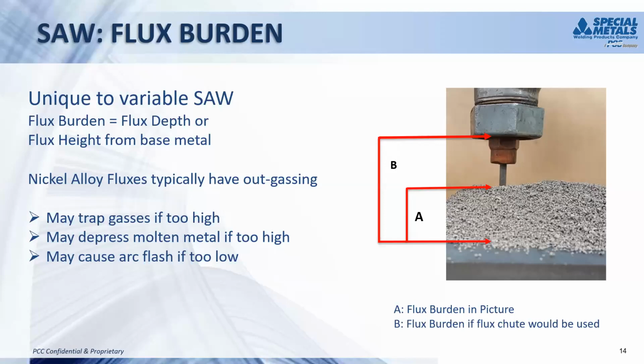If that burden is too low, you do tend to get a little bit of arc flash. Too much of that can be detrimental to the operators, but there are a couple scenarios with some particular nickel alloys that solidify very quickly, where most of the guys that run that in submerged arc do actually want to see just the hint of a little bit of arc flash coming through, because they want to just barely cover that weld puddle so they don't trap any gas. They give it as much time as the gases need to outgas on that weld, so they don't solidify and trap it and get porosity.